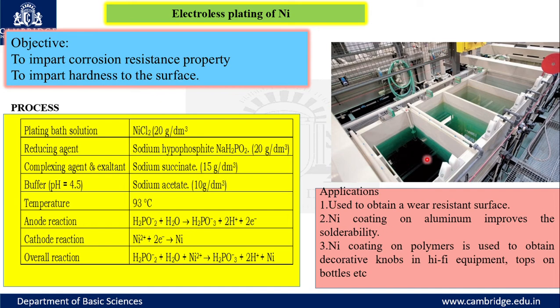What does that mean? That means in this plating solution, all the nickel ions should not be in a free nature. See, if the number of metal ions present in the solution is less, the process will take place gradually and you will get a thin and uniform deposit all over the object. Otherwise, what happens? The movement of the metal ions towards the substrate will rush, and that will result in a bad deposit or a black deposit. So to avoid such a problem, a few of the metal ions should be bound with a complexing agent. As and when required, it will release them gradually. So to bind the free metal ions, we use a complexing agent. The quantity required is 15 gram per dm cube.